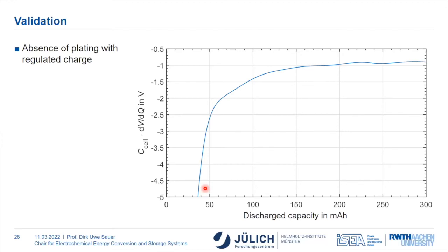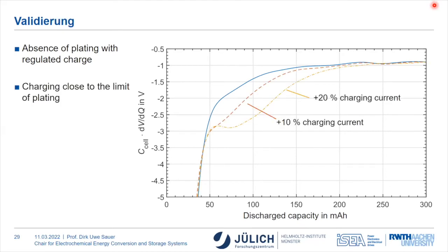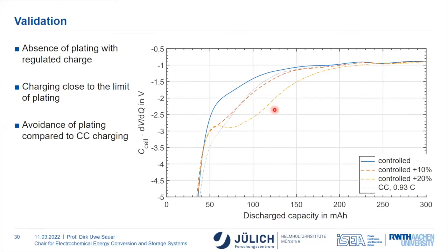Yeah? So the battery is after the charging for sure discharged, and from looking to the deep analysis of the voltage curve, we can see if there was lithium deposited, metallic lithium, and we can see this as an example here. This is the standard curve here we applied, and we increase the current rate by 10% or by 20%. We can see that the curves are obviously changing, and this is a clear indication that we have the battery for a longer period of time on the lithium potential, and therefore this is an indication for having the metallic lithium here available. And the dotted line here is a constant current charging in addition.